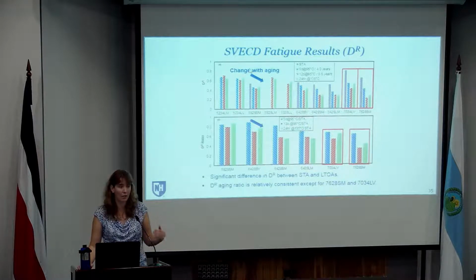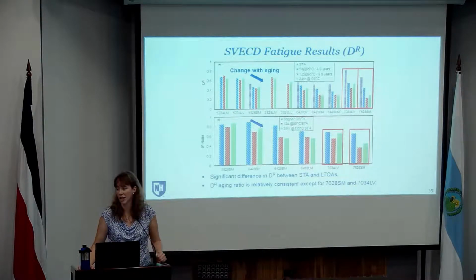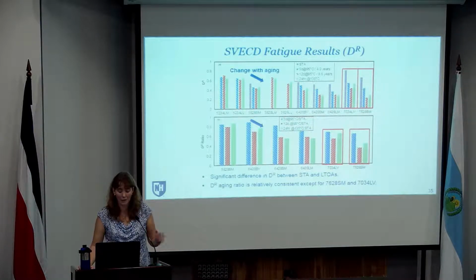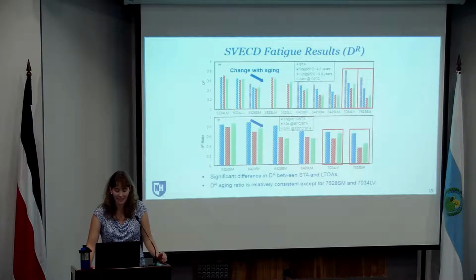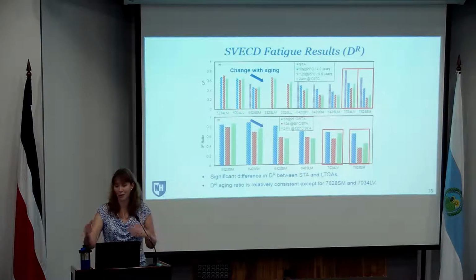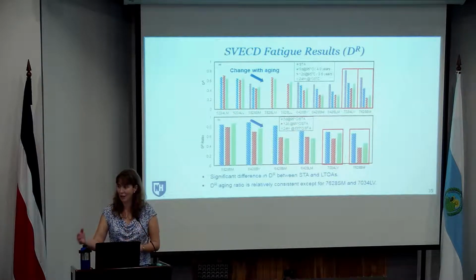tend to have a bigger drop, or more of a change with aging than some of the other materials. But it's not just important to look at that, but also recognize that even if they have a larger drop, once they're aged, those values still are better than some of those traditional materials. So they can age more rapidly, or change more rapidly under aging conditions, but even under the similar aging conditions, they still might be better in the end. So you've got to look at both things.